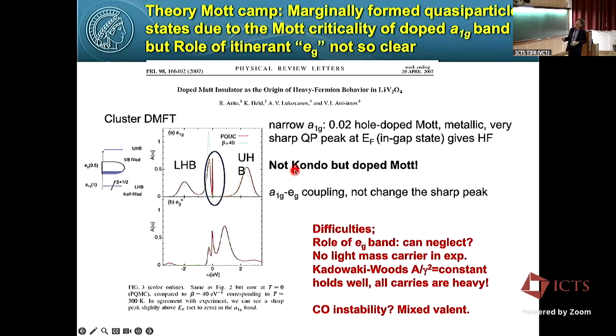On the other hand, my old colleague Arita said the Mott insulator is kind of a basis for heavy fermion behavior. So I think it's a similar story to Anisimov. They said A1g splits into an upper Hubbard and a lower Hubbard band, but it's not an orbital-dependent Mott. They said this state is 0.02, 2% hole-doped Mott state, creating a sharp quasi-particle in-gap state at the Fermi level, and that's the origin of heavy fermion. So it's a kind of doped Mott insulator. That was their picture, and they said A1g-eg coupling doesn't do anything, and they ignored the eg.